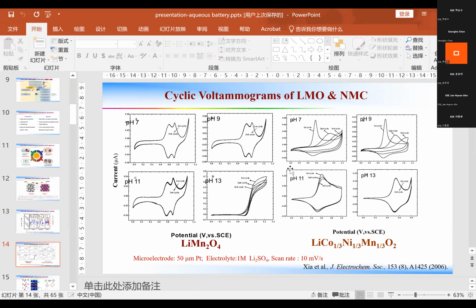But the most interesting, we applied a microelectrode. We use a 50 micron platinum microelectrode to do cyclic voltammograms of the spinel and layer structured materials. It's quite interesting. The spinel is stable over a span of pH values, stable in the pH from 7 to 13. But the layer structured materials are not stable in the low pH electrolytes, like pH 7, but are stable in the high pH, the alkaline electrolytes, for example pH 11 or so.